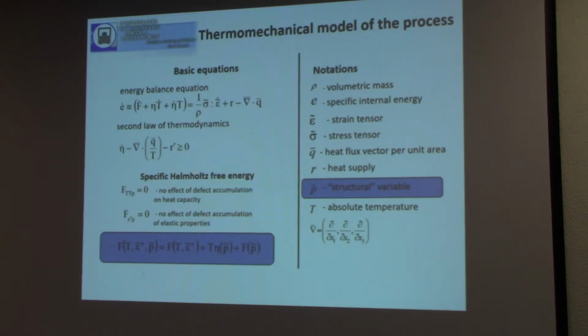Here, during my presentation, there were several bifurcation points. For example, this is one bifurcation point. If you propose that there is no effect of defect accumulation on heat capacity, we can write this equation. A few months ago, a book was published by Professor Raniecki from Poland, and he has shown that if capacity is a function of plastic deformation, we can add additional items to this equation. And we spent a lot of time measuring the evolution of capacity as a function of plastic deformation.